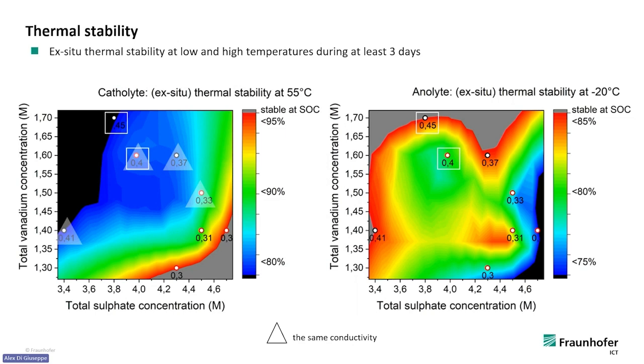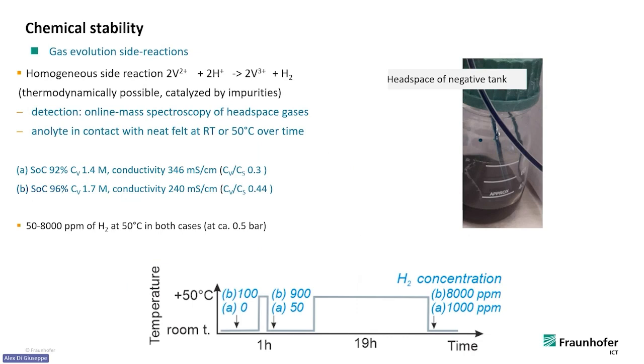And so we identified that, for example, if we dilute it to around 1.4 mole per liter, we don't lose too much of the originally 1.6, but if we increase sulfate concentration, we would gain much more in stability in our electrolytes. The problem is this is only one aspect of electrolytes. The temperature is one aspect, but all the others have to work. Especially when you go to higher temperatures, the stability of the negative pole electrolyte is also at risk. Usually the negative electrolyte is somehow stabilized, kinetically hindered. It would decompose to vanadium-3 and hydrogen thermodynamically, but this is hindered. But if you increase the temperature, this reaction can get more favorable.